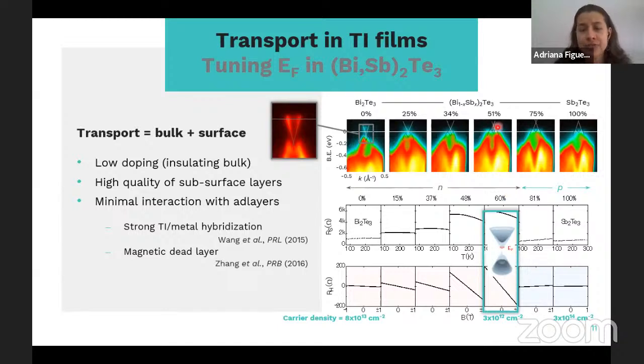And this is relevant because this optimization was performed as well by Frederic Bonnel. With this concentration, we are obtaining the optimal properties in terms of magnetotransport for this kind of material, this BST, bismuth antimony telluride alloy. And that way we can incorporate it into our devices to study even more properties of it.